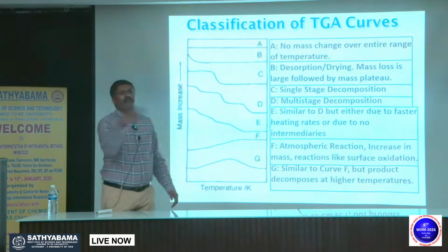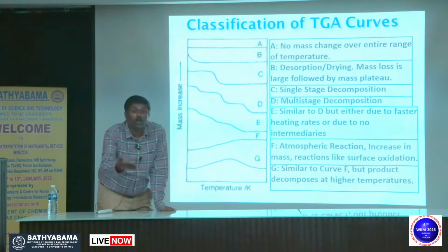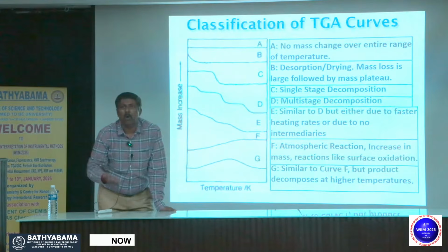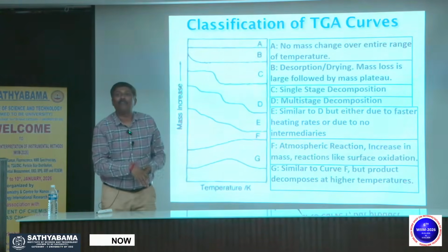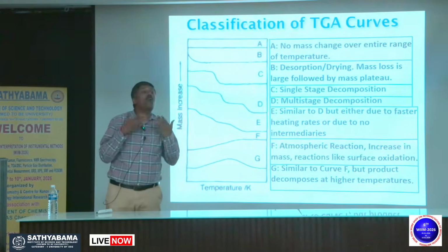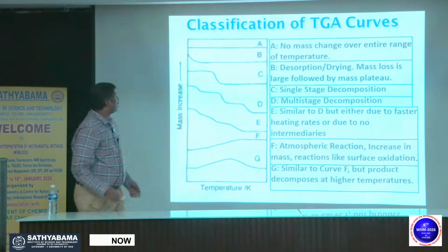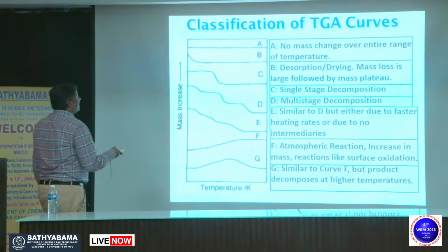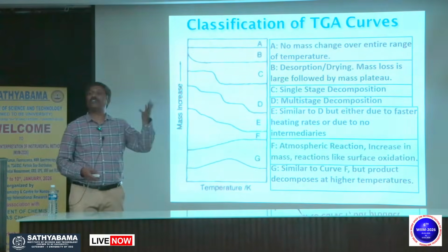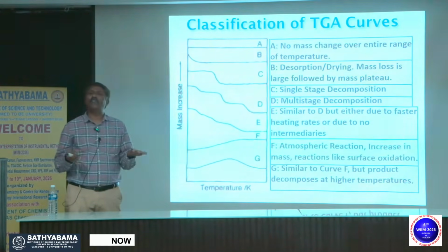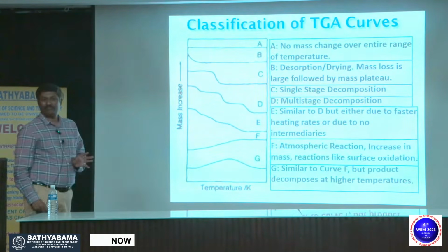It's like if you slap someone once and ask if it hurts, and give a pause for him to answer yes or no, but you keep on hitting. Before he answers, again slap. What will happen? You have not given a time to respond. So, it could be multi-stage decomposition, but heating rate is faster, or not so many intermediates, or some problem with the instrument, or heating rate.